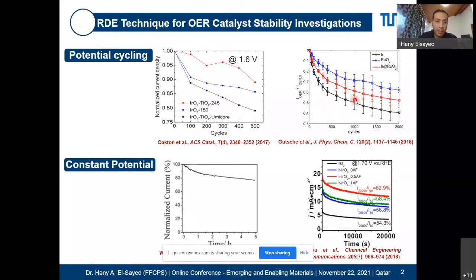Here's another example. And that's not the only method. You can also use a constant potential. You can apply a constant potential, of course, in the region where the oxygen evolution reaction is taking place, and you can monitor how the current goes with time. That's one example, and here's another example. Again, what you conclude out of this is that the red line, which stands for the specific catalyst, this catalyst here, is the most stable catalyst. Why? Because it doesn't decay quickly, according to this paper.